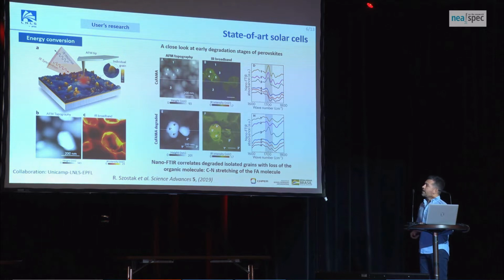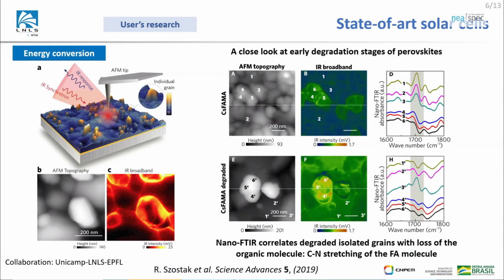So here, basically they were studying using SNOM, more specifically nano-FTIR, to study early stages of degradation of these perovskite films. So first of all, as we have a broadband beam, we usually do these broadband images, which bring us a kind of broadband reflectivity response of the material. And we could see already some disconnection between topography and this IR signal.